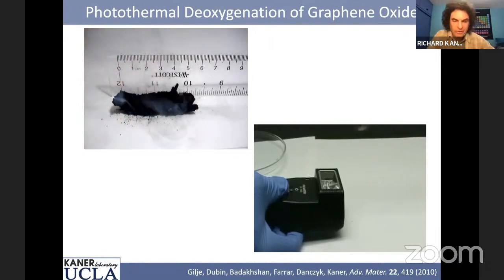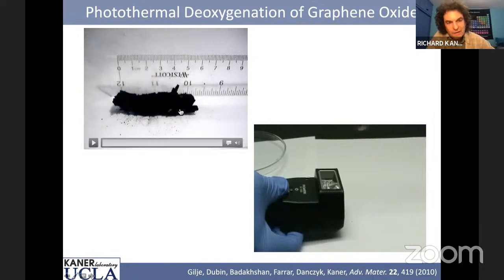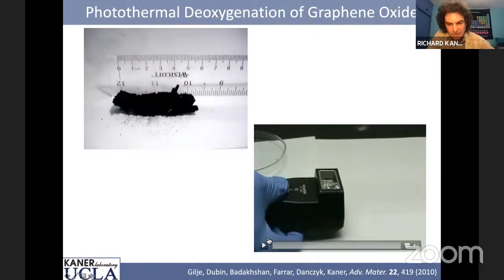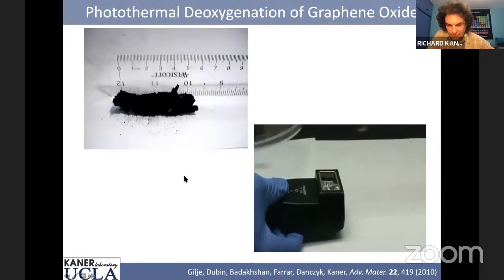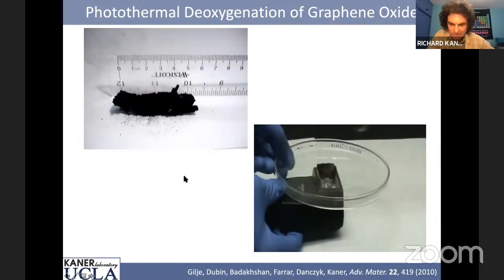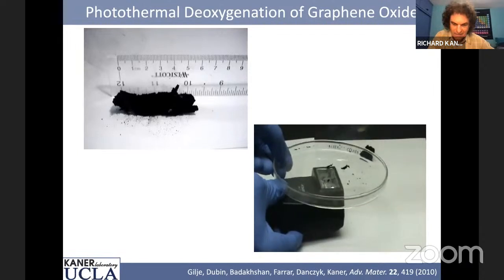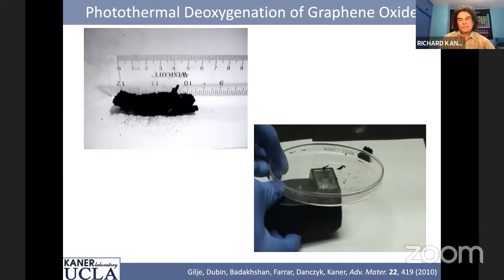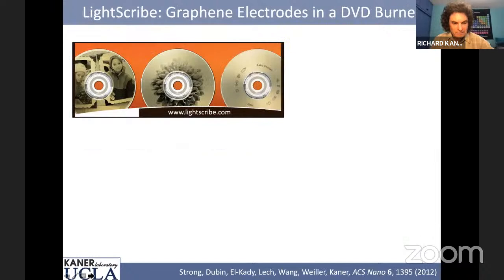It looks like it's burning, but in fact, you'll see that most of what's left is this black carbon. And so what it's really doing is deoxygenating. It is burning, but what's going off is CO2. And you can do this with graphene oxide paper and a flash of light. So here's a camera flash. We bring up the graphene oxide paper, hit it with a flash of light. And you see it absorbs the light, it gets hot, and again, it blows off CO2. So two completely uncontrolled reactions. But it's possible to control these.